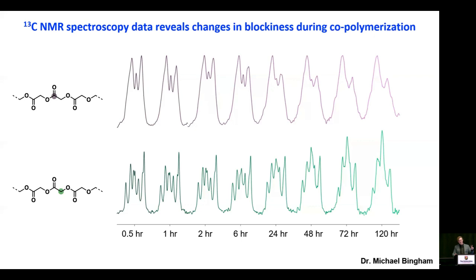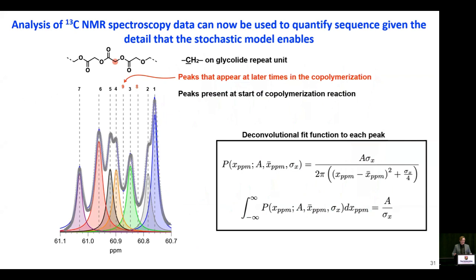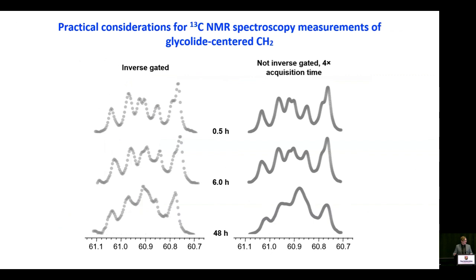And you'll see, first there's actually several peaks under there. We're not sure what they are, but it varies over the course of about 24 hours and not much after that. If you look at the glycolide-centered methylene, though, there in green at the bottom, you'll see that it's spread out, there's a lot more information there, and it continues to evolve over 120 hours. Another benefit of this signal is that it does not depend very strongly on stereochemistry. It's largely compositional only. And so we set out a spread of deconvolution fit functions so that we could separately interrogate the change in population of each of these signals and figure out what they correspond to, okay?